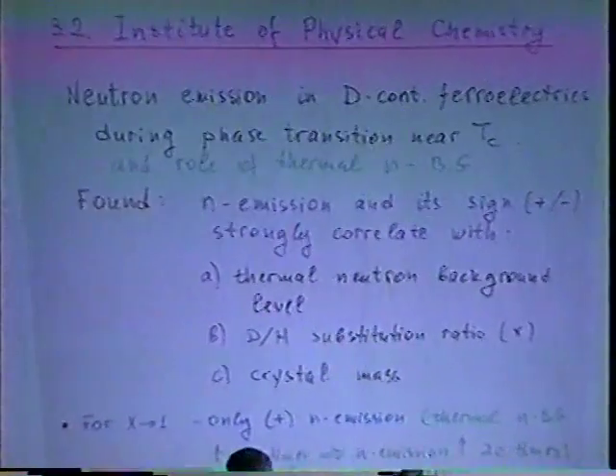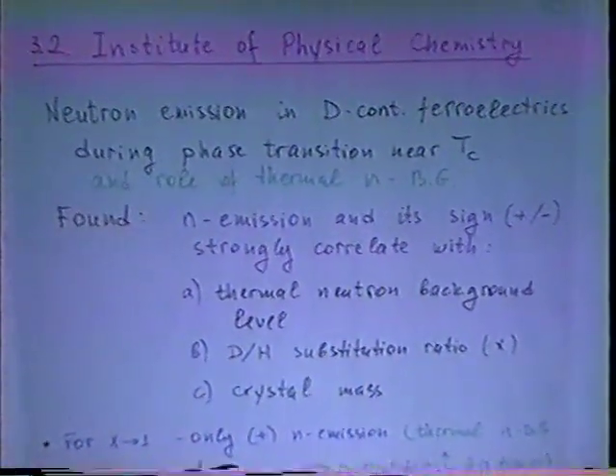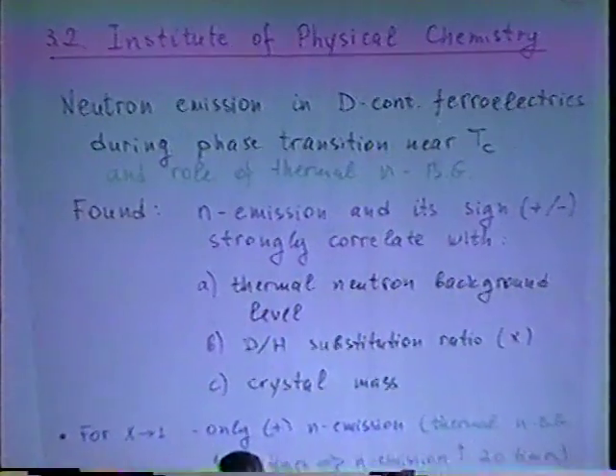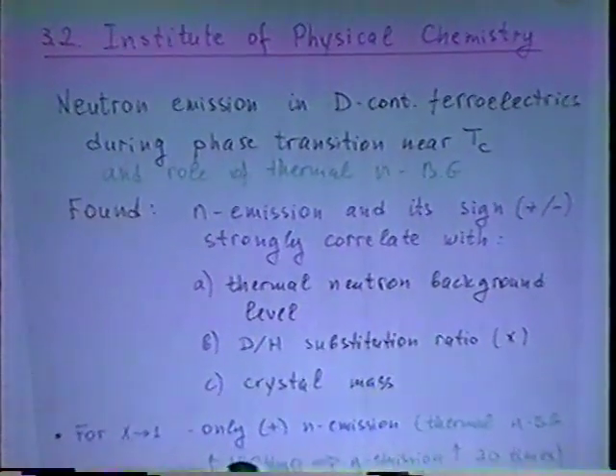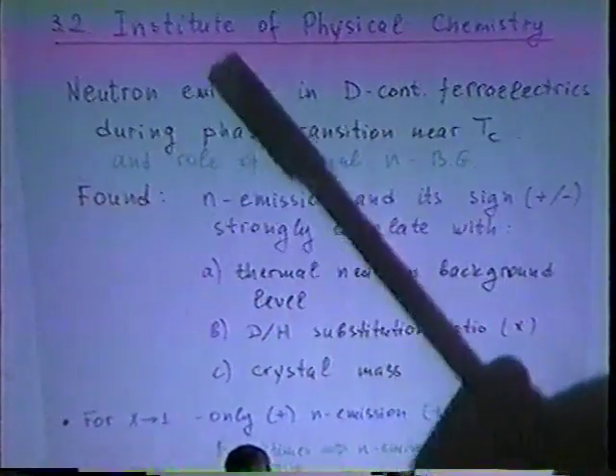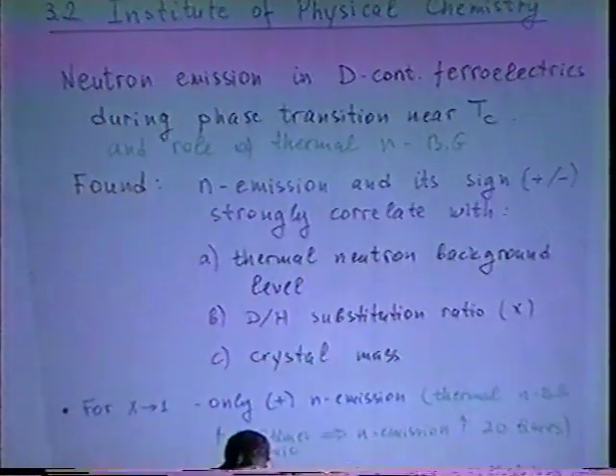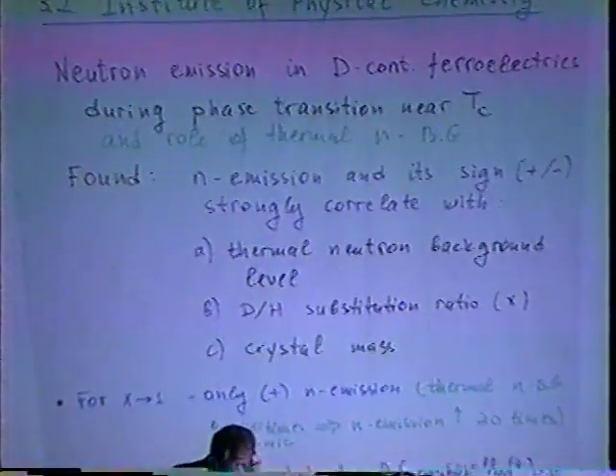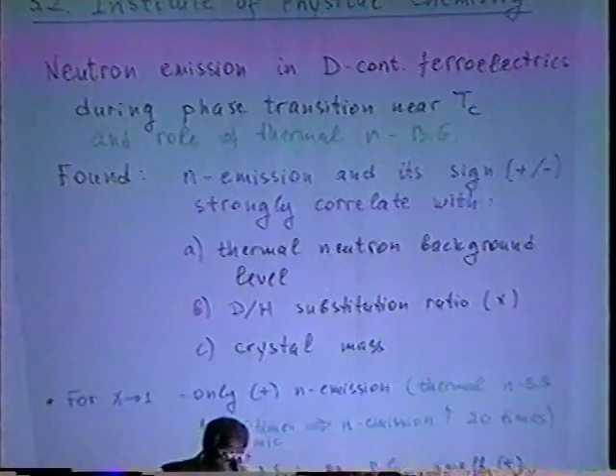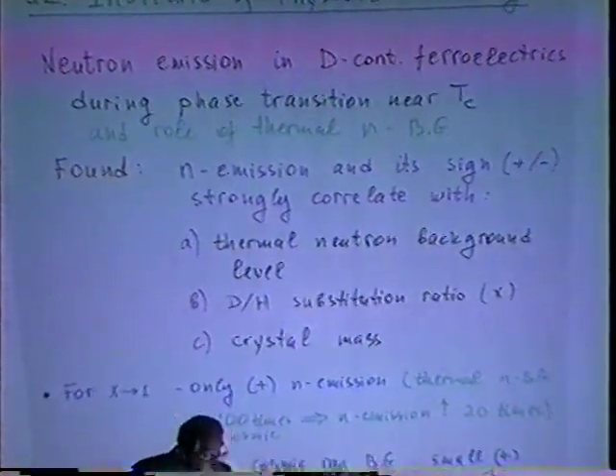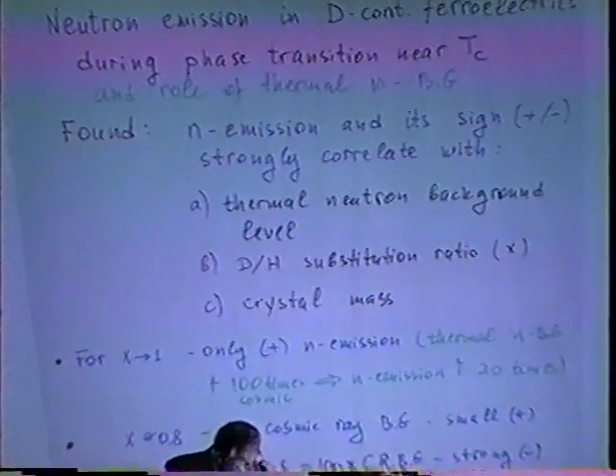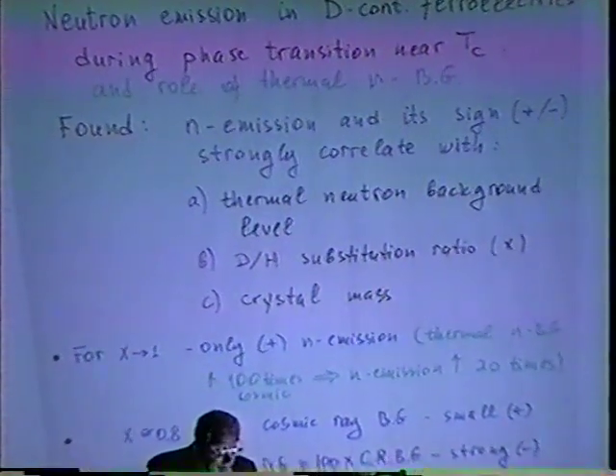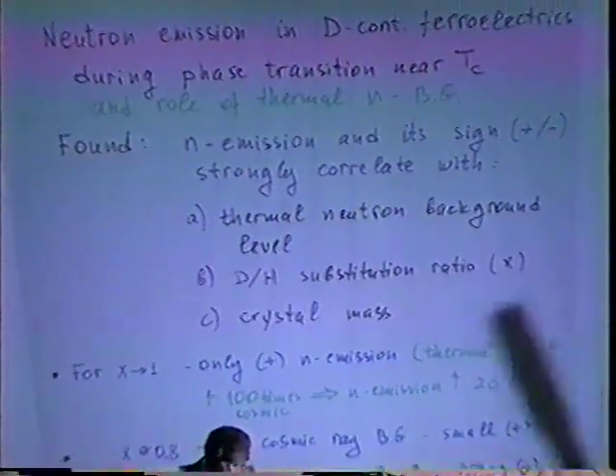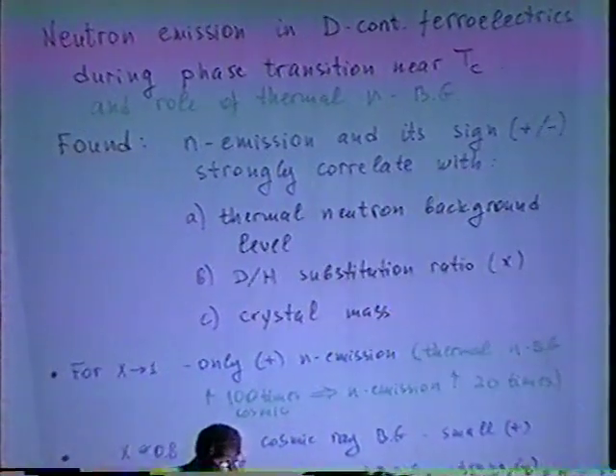The other work done with ferroelectrics is the experiment at the Institute of Physical Chemistry. They measured neutron emission with deuterated ferroelectrics during phase transition near the Curie point. They also studied the role of thermal neutron background. What did they find? They found that there is a neutron emission, and the sign of this effect, I'll explain it later, strongly correlates with